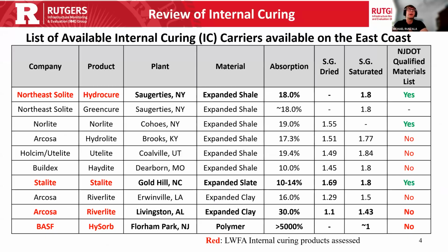We tested the products in red, starting with Northeast Solite's product HydroCure. It's an expanded shale product. Most internal curing carriers are expanded shales. This is the most common expanded aggregate type. It's produced in New York, and the absorption is typical of this class of material at 18%.